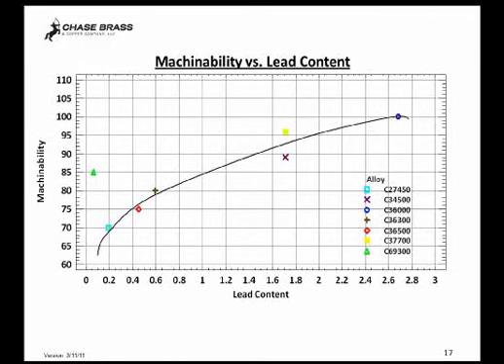For example, what does not fit on the curve is alloy 693, which uses that three-phase microstructure to get much higher machinability than you would expect based on the lead content. As I mentioned, there are some other alloys that contain other materials, whether it's bismuth or tellurium or sulfur, that do the same sort of thing. They have very low lead contents, and they have higher machinability levels.